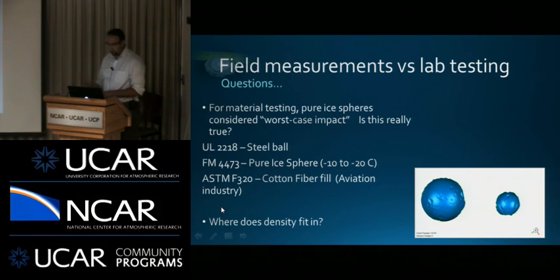And then an interesting one to drop the density of stones, the ASTM F320, this is an aviation test, uses cotton fiber fill to drop the density of their laboratory stones. And the last question there is where does density fit in? Out in the field, when you're just measuring 2 dimensions, the non-homogeneous shapes of hailstones make doing a density calculation almost impossible. And if you want to do an immersion test, does that affect the compressive strength test? And is that practical to do in the field? Can you sit there and immerse the stone in a liquid, get your volume that way? Is it too cumbersome? We haven't actually tried that, and I'd like to give it a stab.